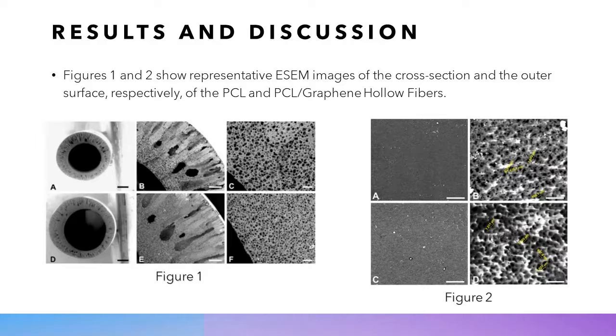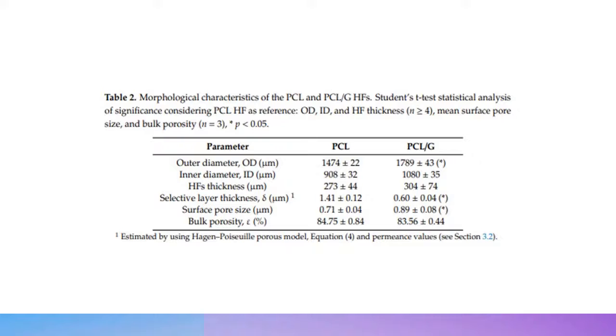The ESEM images of the outer surface of PCL (Figure 2A) and PCL graphene (Figure 2C) hollow fibers show uniform surface morphology. At a higher magnification, Figure 2B and D, the values of mean surface pore size could be estimated. Here in Table 2, morphological characteristics of the PCL and PCL graphene hollow fibers. Student's t-test statistical analysis of significance considering PCL hollow fibers as a reference. Mean surface pore size, size, bulk porosity.